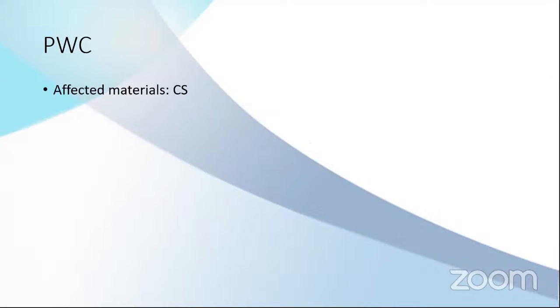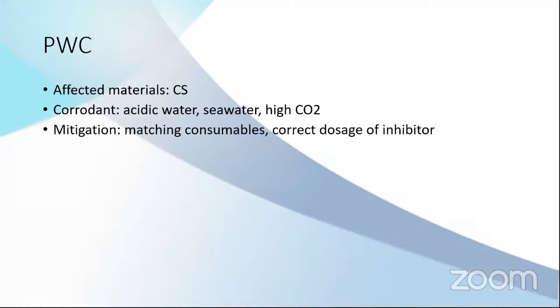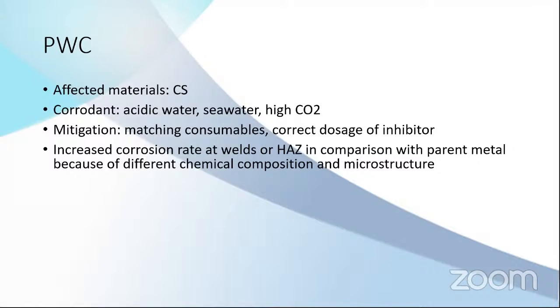Affected materials are carbon steel. The corrodant is the corrosive element that can cause the corrosion: acidic water or low pH water, seawater, high CO2. So it's like a carbonic acid. In preferential weld corrosion, the weldments are corroded faster than the parent material. To mitigate, use matching consumables and the correct dosage of inhibitor.